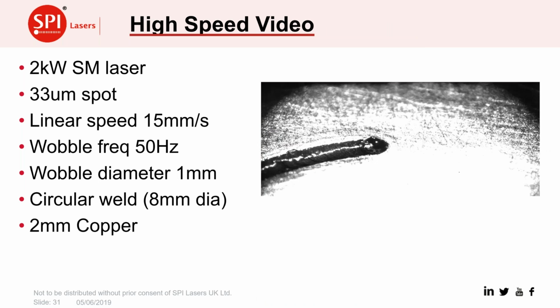This is just a bit of video. It says high speed video, but it actually runs slowly, as it's obviously a slowed down picture, just so you can see what's happening. You can see the weld pool being dragged around as the beam moves around in the oscillation of the weld. It's a very stable weld pool, and that is the reason why we can make these welds on copper at reasonably high speeds, but with very low spatter. Because of the high power density of the laser, it is a very stable weld pool.